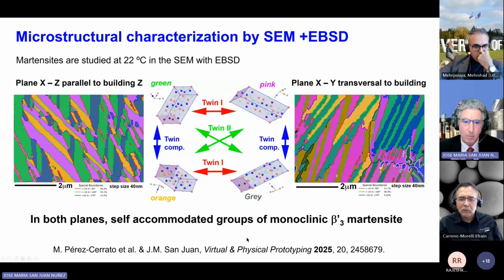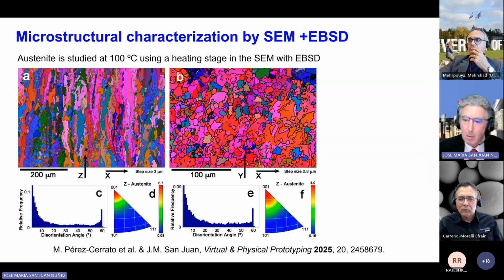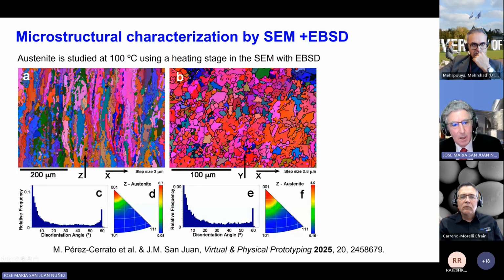So we get a good martensite, and then we move to the characterization of the austenite. To characterize the austenite, we have to heat up above the transformation temperature. So the austenite is studied at 100 degrees centigrade using the heating stage and at the SEM with the EBSD. And what we first observe is that this is the build direction of the welding process. So we have a columnar structure that is developed along the welding direction that exhibits a really strong texture on the 001 direction of the austenite.